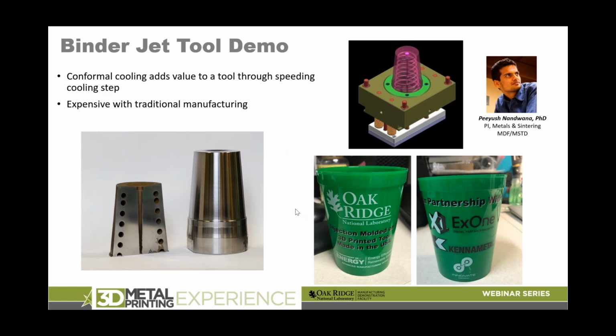This demonstration is with H13 tool steel, and it's just an injection molding tool, as you can see. But what was cool is that we put the conformal cooling channels into the print, and it didn't really cost us much extra to do that. It's a little extra depowdering time. And they were able to sinter that, get it machined down, and demonstrate it on an actual injection molding setup. So that was really exciting.